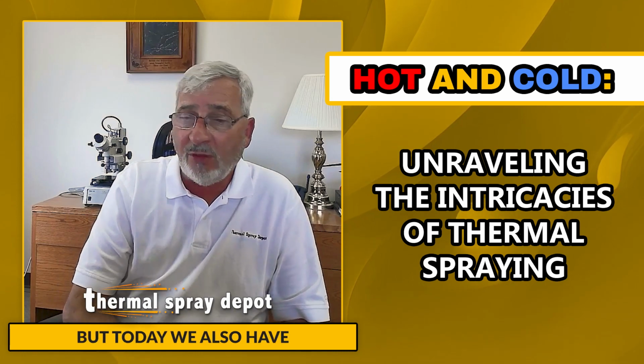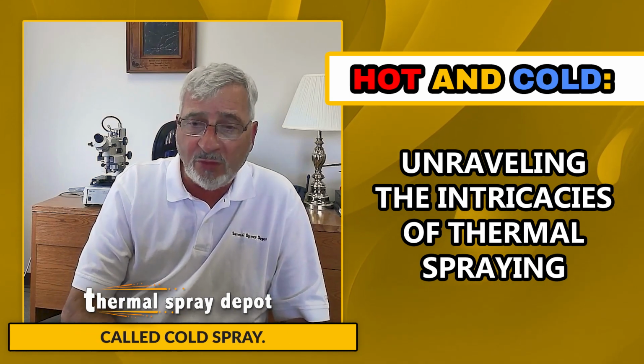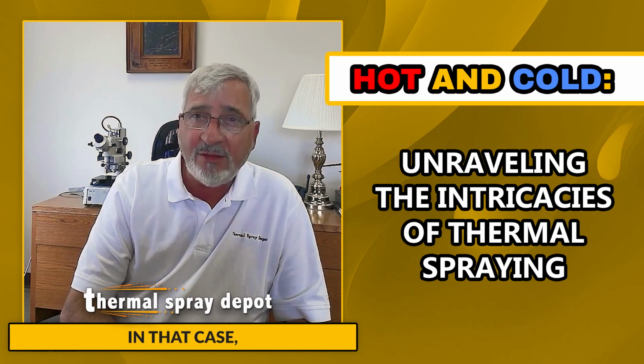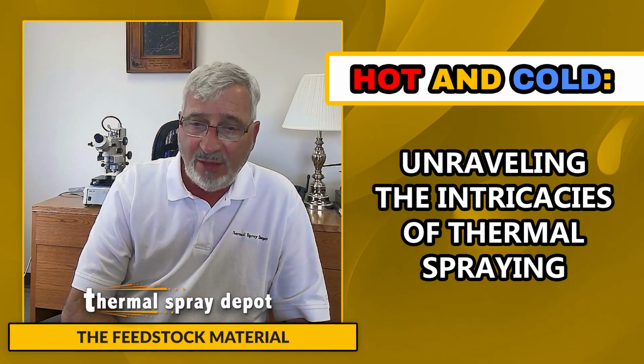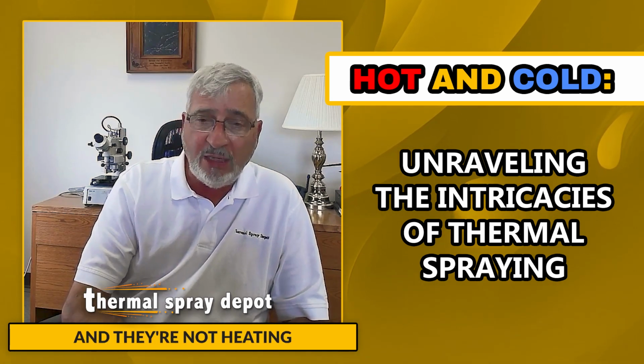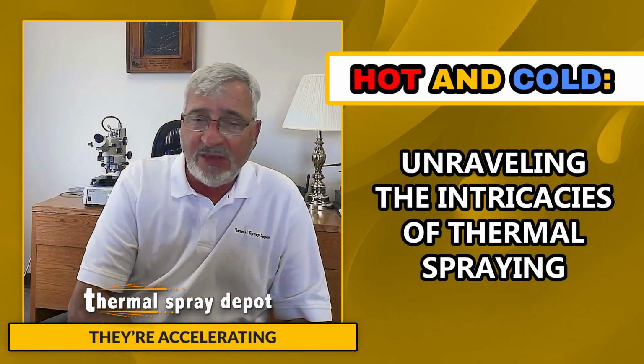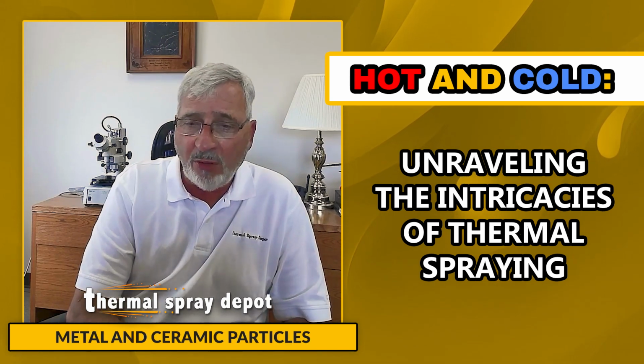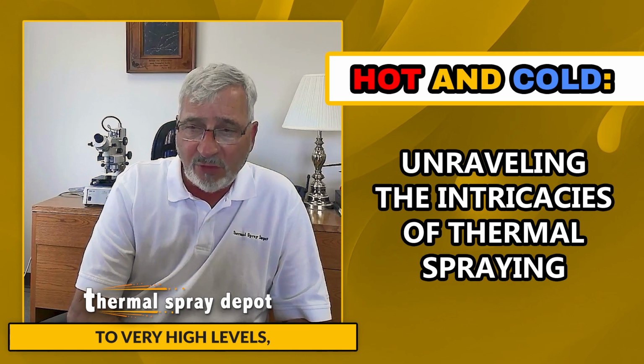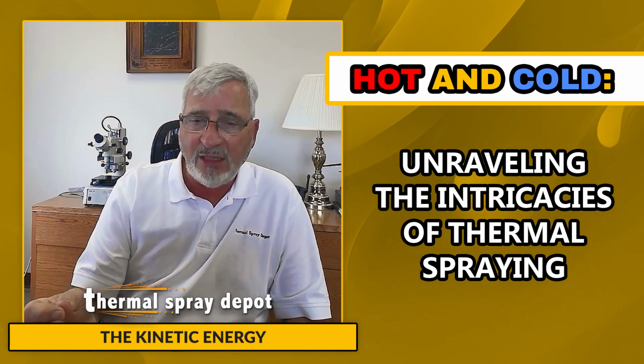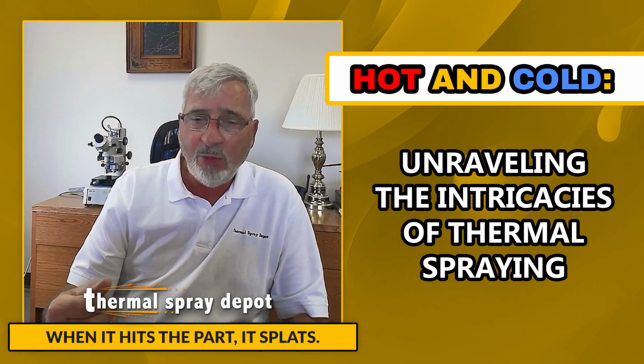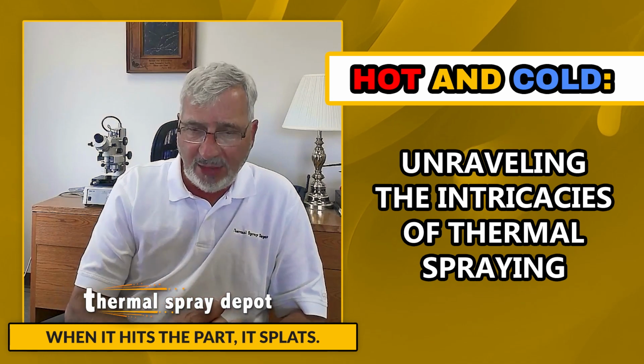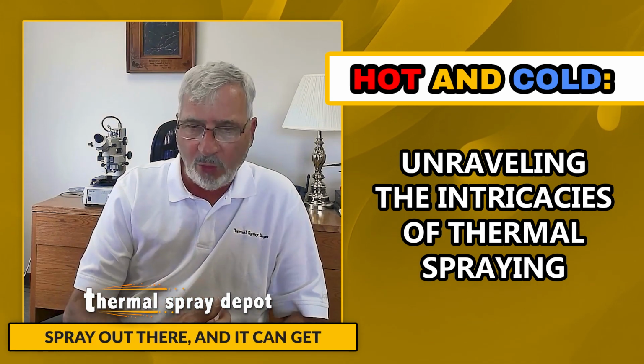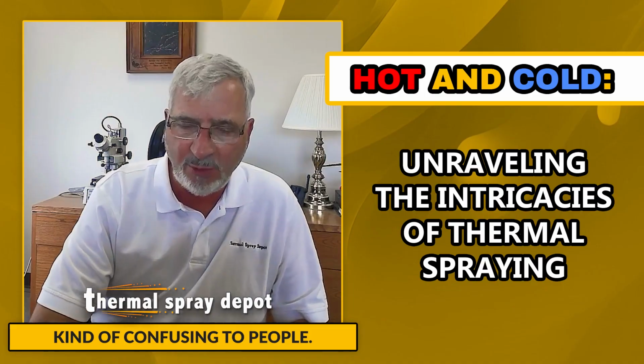But today we also have another process called cold spray. In that case, they're not melting the feedstock material and they're not heating the part up. They're accelerating metal and ceramic particles to very high velocities, but not melting them. And it's the kinetic energy of the high velocity that, when it hits the part, makes it splat. So there's two kinds of cold spray out there, and it can get kind of confusing to people.